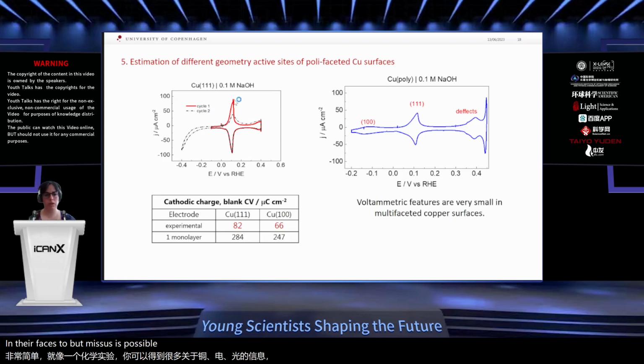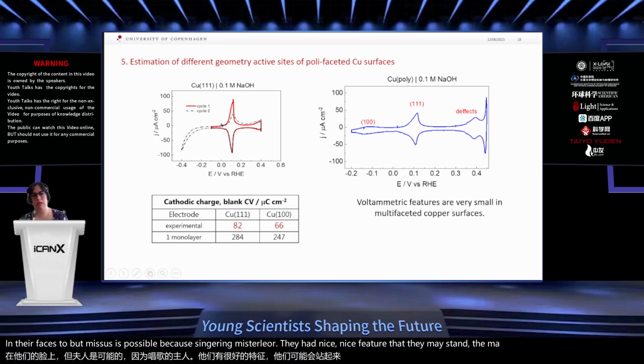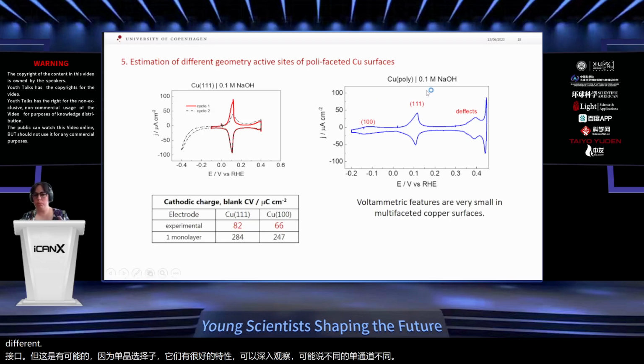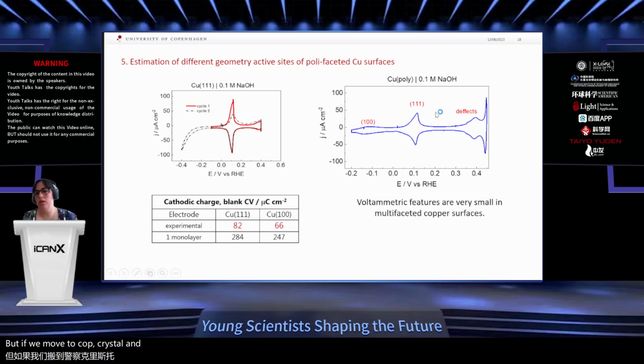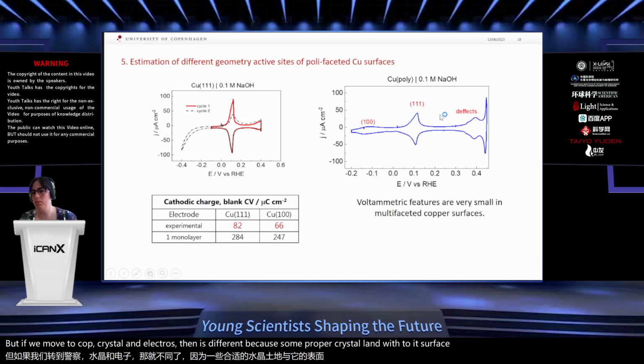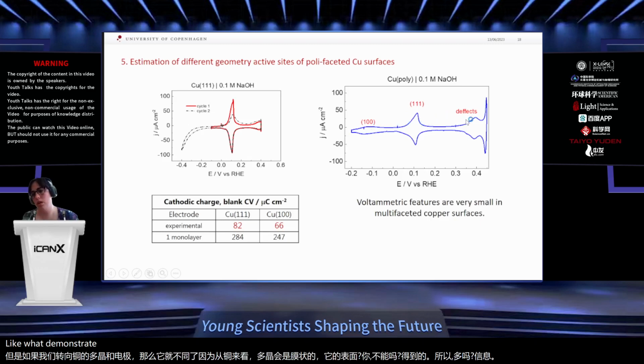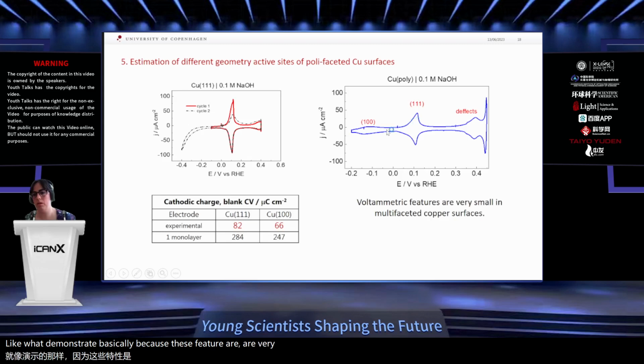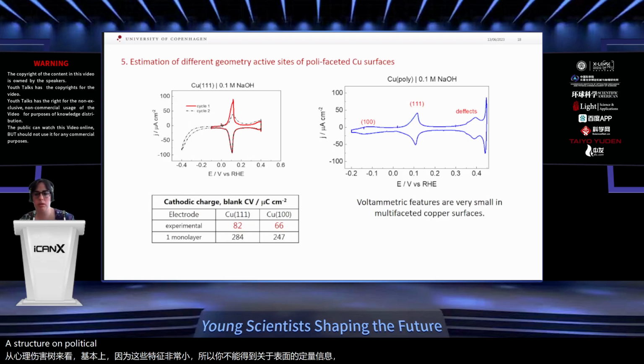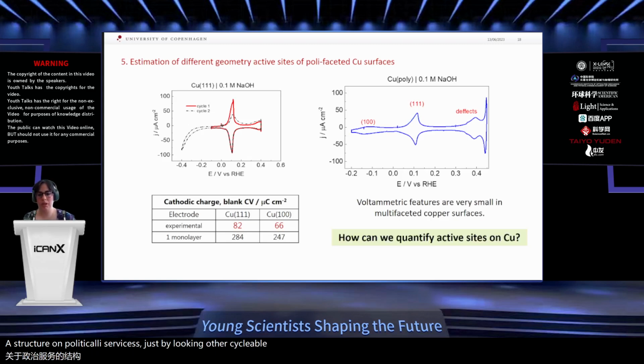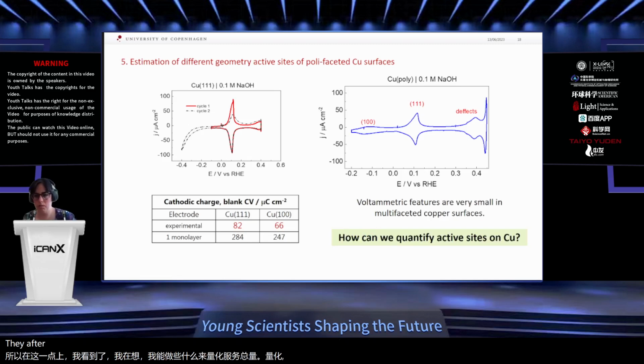But this is possible because single crystal electrodes have nice features that make different single phases different. But if we move to copper polycrystalline electrodes, then it's different, because on a copper polycrystalline multifaceted surface you cannot get so much information from cyclic voltammetry, basically because these features are very small. So you cannot get quantitative information about surface structure on polycrystalline surfaces just by looking at the cyclic voltammetry. So at this point, I was thinking, what can I do to quantify the surface structure, to quantify the active site on copper of different geometry?